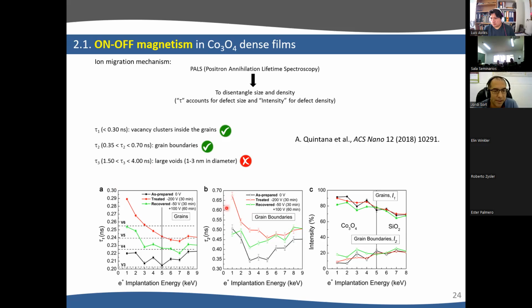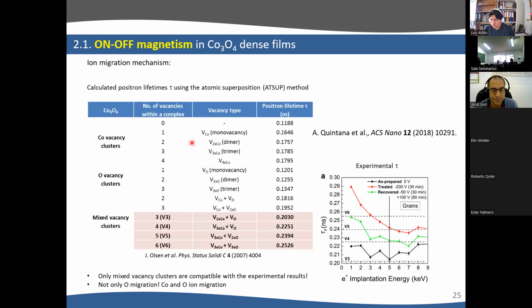All the times we have in our experiments correspond to vacancies inside the grains or the grain boundaries. Then you can do, well, actually, our colleagues did some calculation using this atomic superposition method. And the conclusion is that from the times we get, we don't have only oxygen vacancies. So we have complex vacancies which involve cobalt and oxygen at the same time. So the initial picture I showed where you remove one oxygen ion and leave a hole is not true. Here we have formation of complex vacancies involving several atoms of cobalt and oxygen. That's mainly the conclusion from this technique.